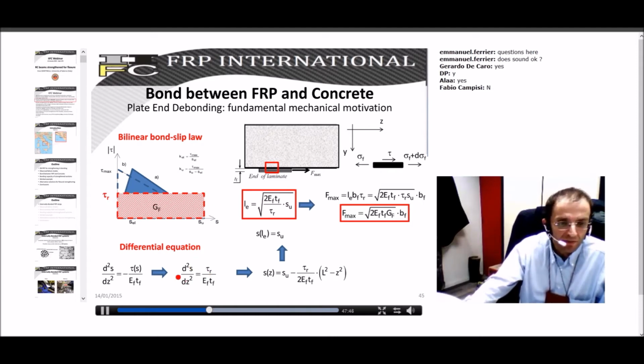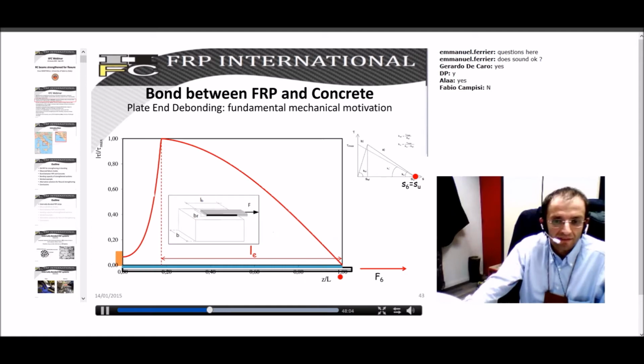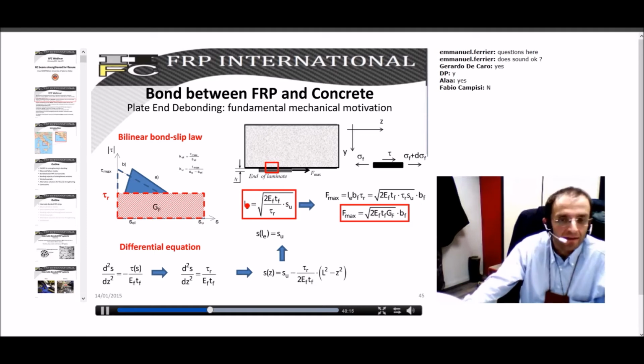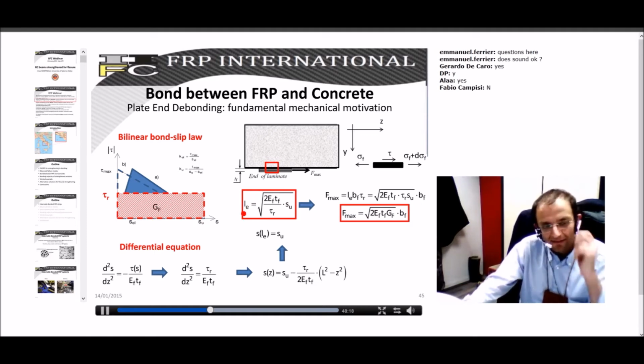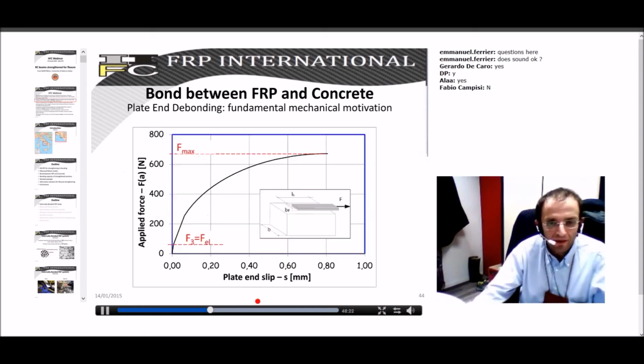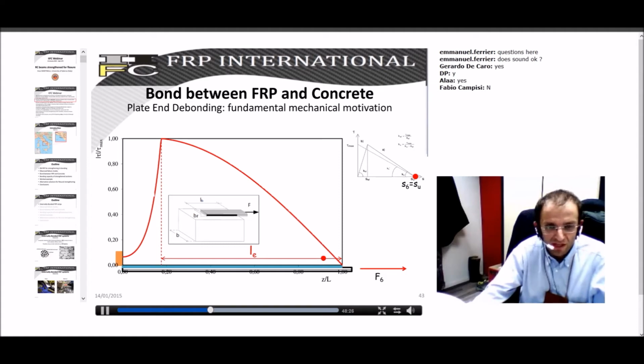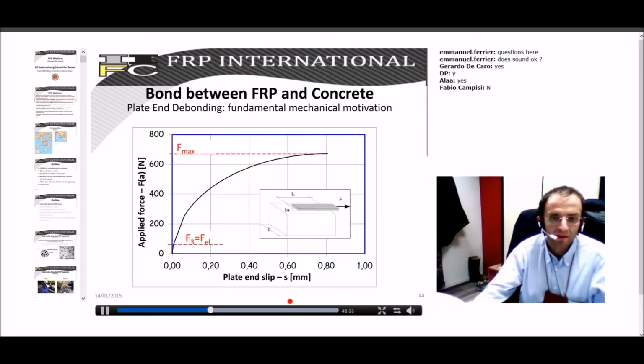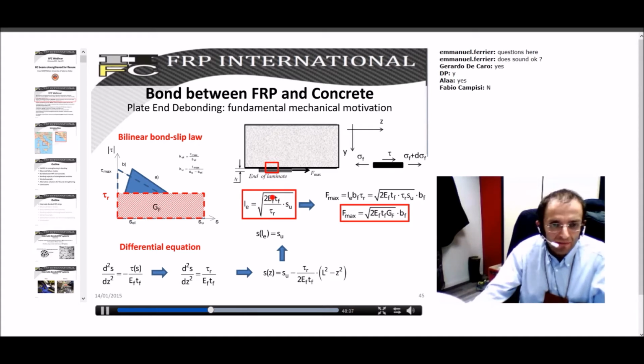This equation is very easy to solve because this is a constant coefficient second order differential equation, whose solution is this one. And if you apply the condition here that the displacement at L equal to LE is equal to SU, as you have here, the displacement at Z equal to LE is equal to SU, what you get is an expression for LE. LE is the transfer length. It is the length between the point in which tau reduces to 0 and the bonding starts developing, and the maximum tau. So this is the LE.